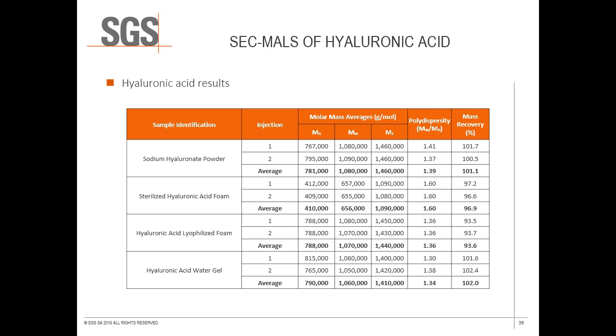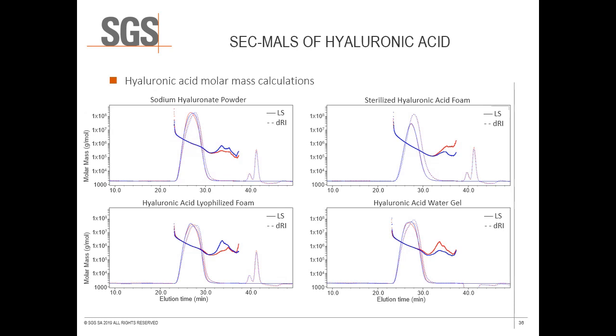It is interesting to note that despite the broadness of the chromatographic peaks, the calculated polydispersity is rather low. This may be due to the inefficiency with which column packings of large particle size separate molar masses. This cannot be avoided, however, due to the size and susceptibility of HA molecules to shear degradation, as previously mentioned. This inefficiency in separation will have a negative impact on the accuracy of M sub n and M sub z calculations. The upward curvature in the molar mass plot in the tail of the peak, whether due to error in calculation from low instrument signal or from anchoring, also has an effect on the calculated number average molar mass, and so the calculated polydispersity must be taken with a grain of salt and is likely somewhat higher than is reported.